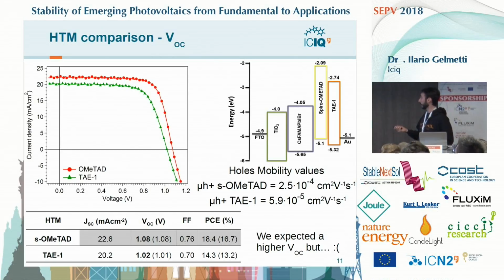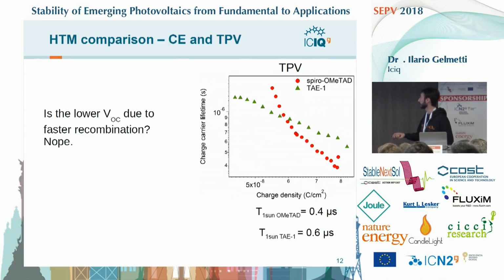Well, unexpectedly, we obtained a lower open circuit voltage, even if the mobilities were just 5 times smaller, so still acceptable. And so we got curious about why we expected higher voltage and obtained lower voltage. And the efficiency obviously turned out to be a smaller value. But okay, we are interested in voltage mostly.